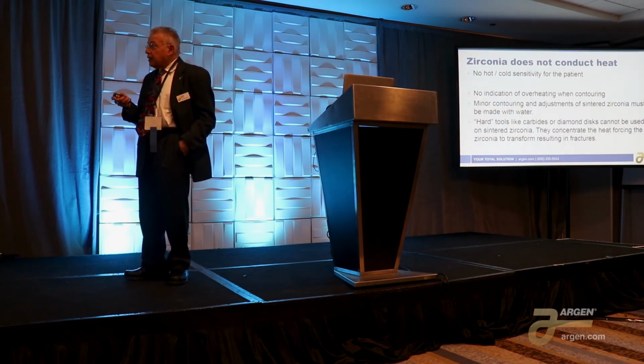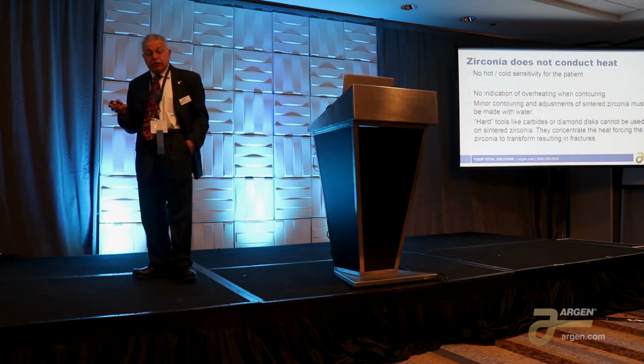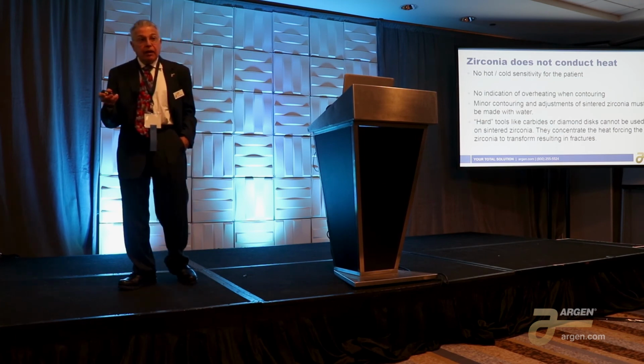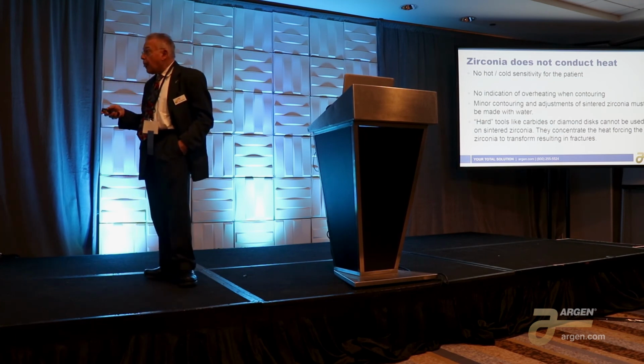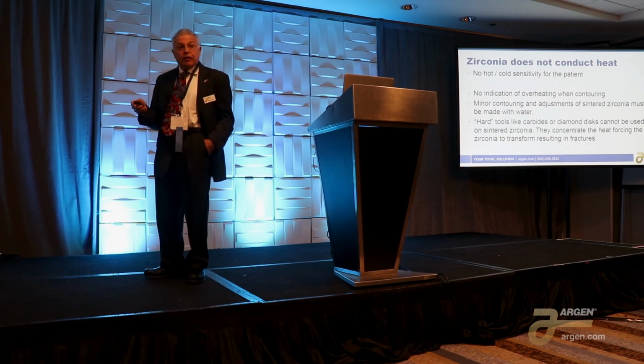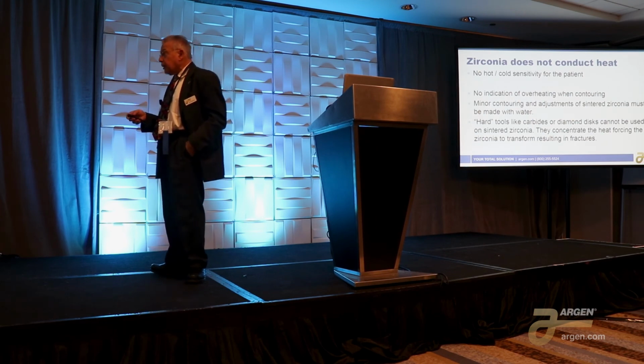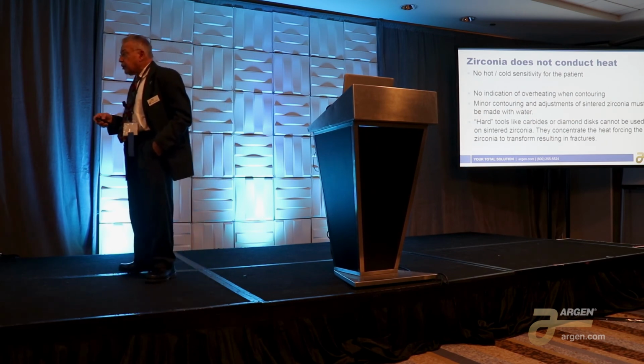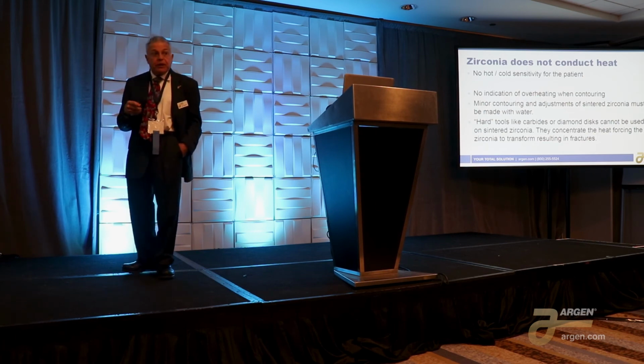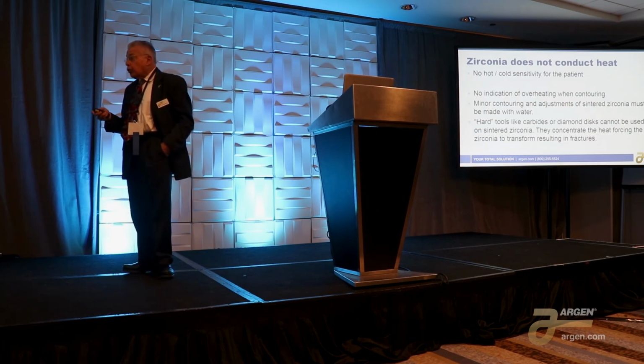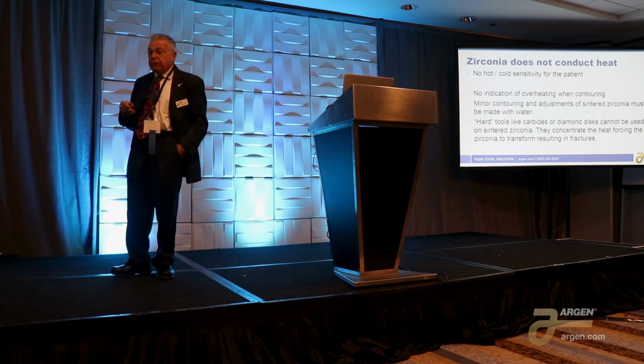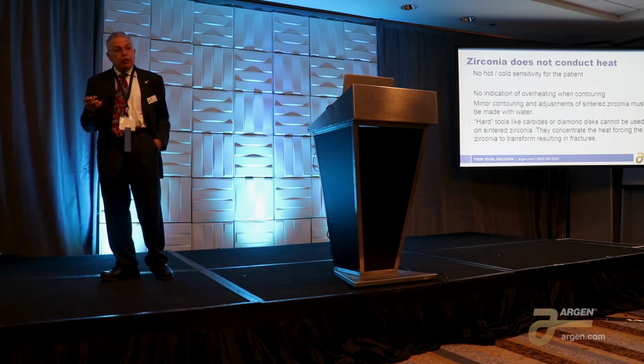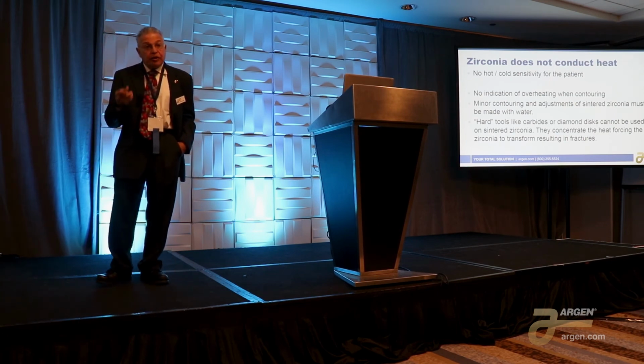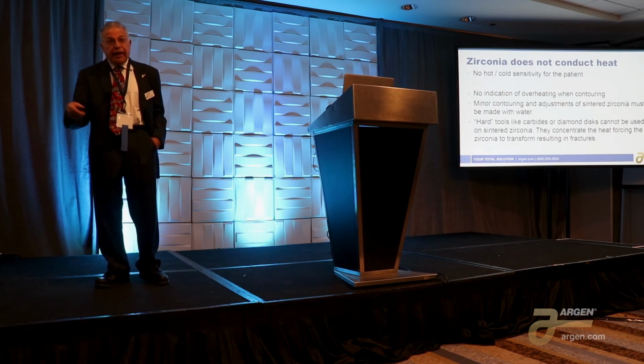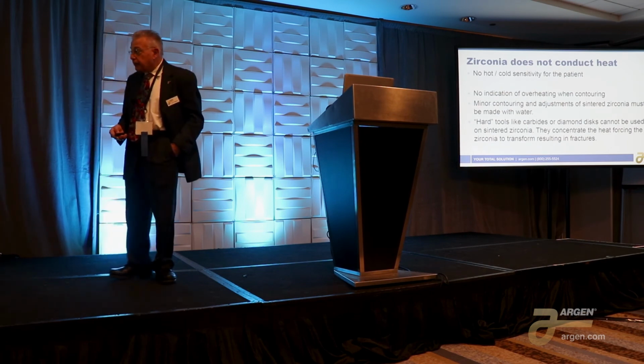Because it doesn't conduct heat, that's great for the patient. There's no hot and cold sensitivity, even on a root canal case. But you have no indication of the material overheating when you're contouring. Any contouring adjustments of sintered zirconia must be done with water. Hard tools like carbides or diamond discs cannot be used on sintered zirconia because they concentrate the heat, which the zirconia can't get rid of, and it'll force it to crack.